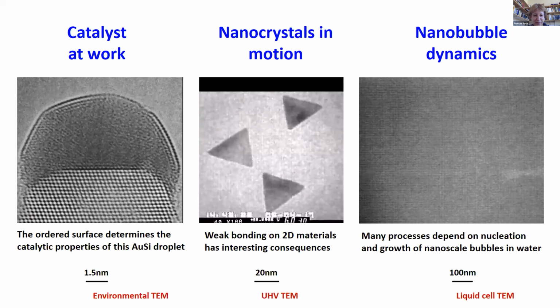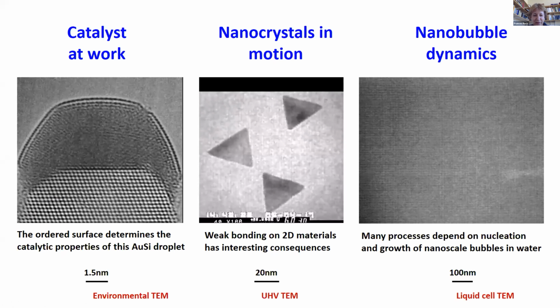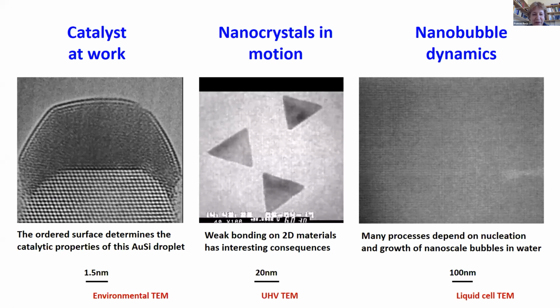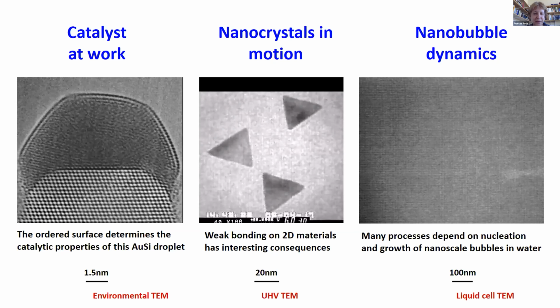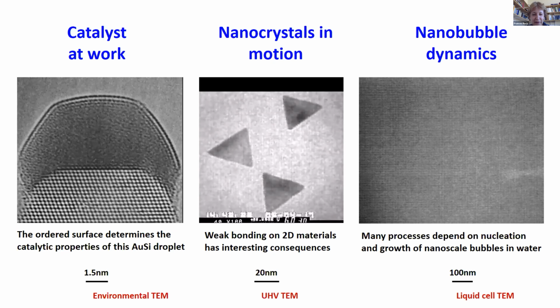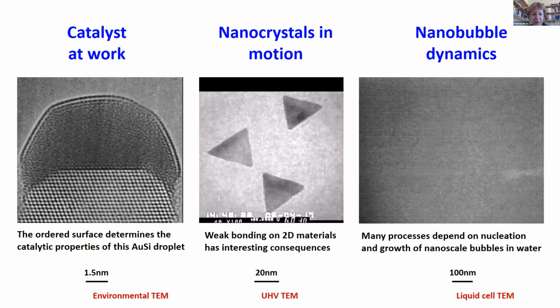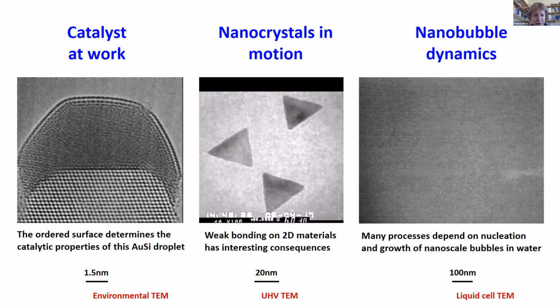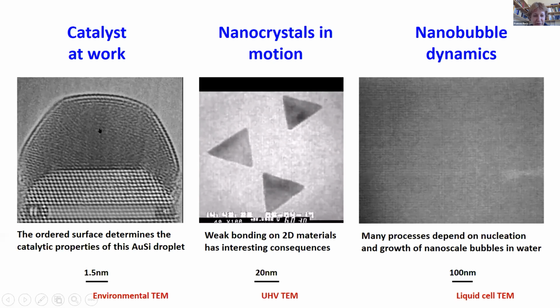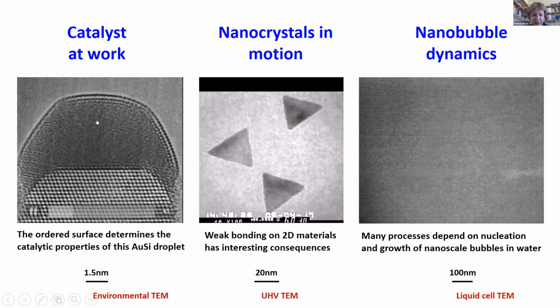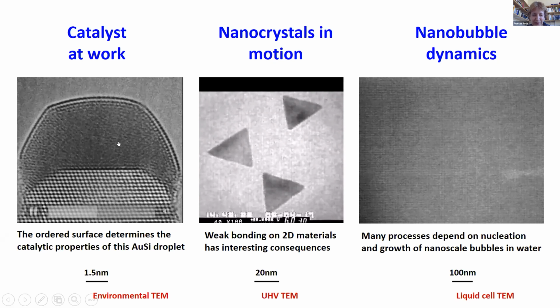So it's a liquid droplet, gold silicon eutectic liquid on top of a silicon post. And what you can see on the surface is a crystalline layer. So the interior is amorphous and the surface is crystalline. You can see some lattice fringes inside the liquid part, but in fact, that's the surface part wrapping around.